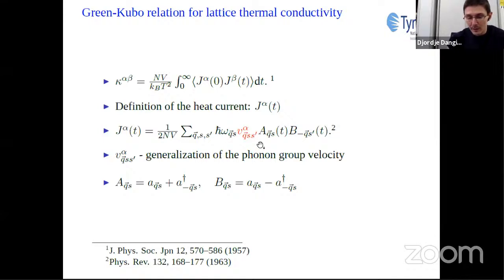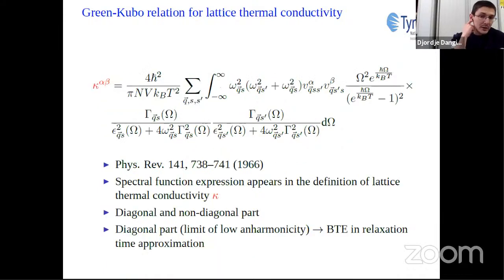Another detail I want to point out here is this quantity V_Q,SS', which is a generalization of the phonon group velocities. The S and S' are the phonon branches, so this goes beyond the standard definition of the phonon group velocity to include the off-diagonal terms in the group velocity matrix in the phonon eigenvector space. The A and B operators can be defined in terms of the phonon creation and annihilation operators, as shown in the last line here. Once you go through the whole derivation of this expression, you end up with an expression like this one, shown in the first line.